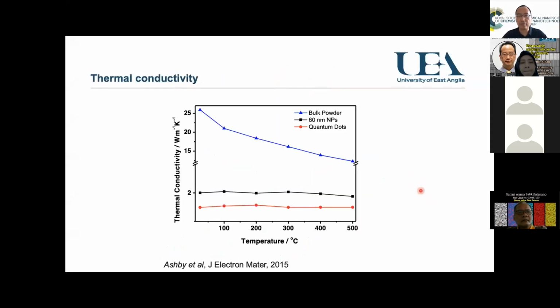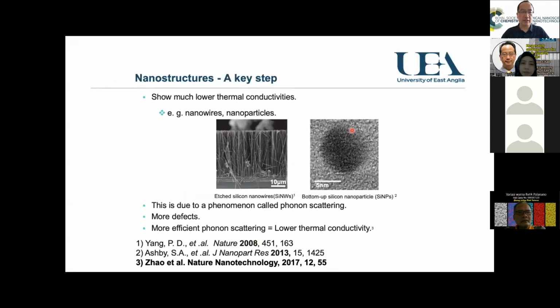And we also did an experiment in our lab. We made a comparison with different size of our silicon nanoparticles and compared with bulk materials as well. So obviously that thermal conductivity significantly reduced. Okay, so yeah, that's theory, right? And we confirmed that with our experiment. Okay, so we did the work, and then obviously our idea is still using our silicon nanoparticles. So some other groups did that with silicon nanowire.